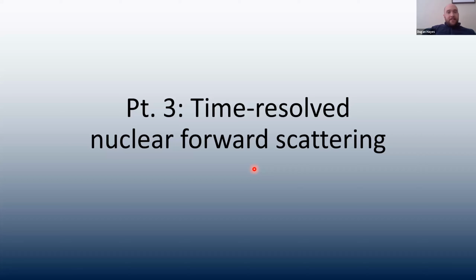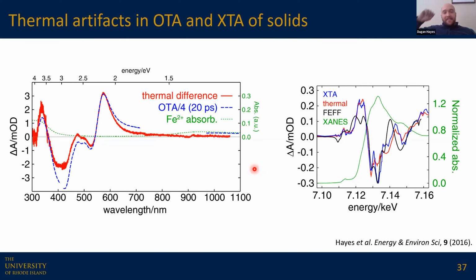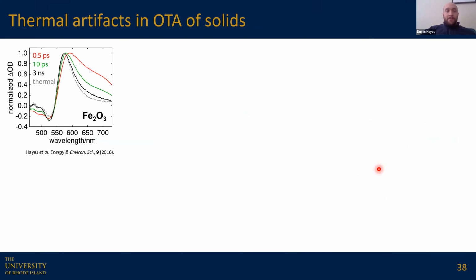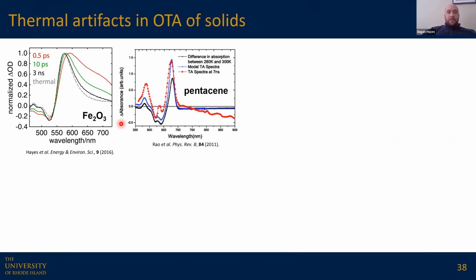So with that, I'm going to shift gears into something a little more exotic, perhaps, talking about our efforts toward time-resolved nuclear forward scattering. This dates back to the work I did on hematite that Lynn mentioned when I was a postdoc at Argonne. And we were troubled to find that nearly all of the optical and X-ray transient absorption signal that we could see from hematite corresponds to laser-induced heating. We were able to identify some signatures that were unique to the electronic excitation, but most of this seemed to be thermal.